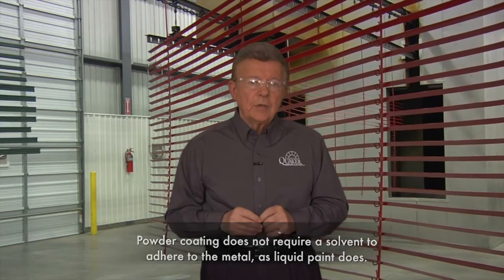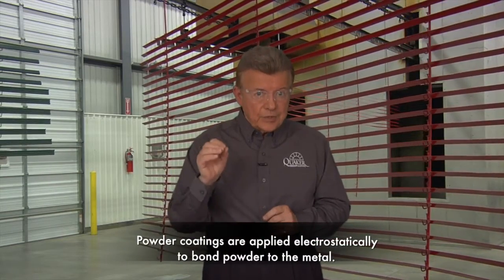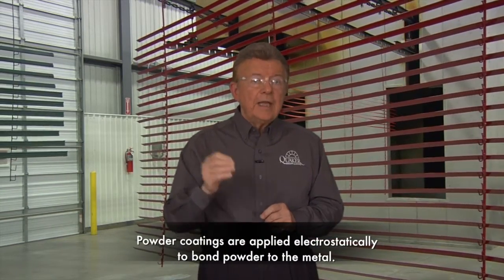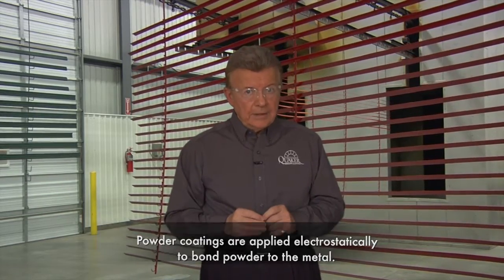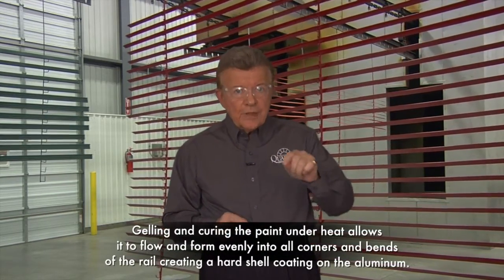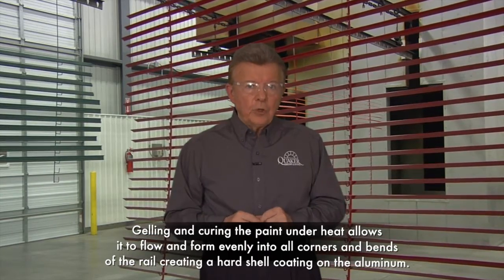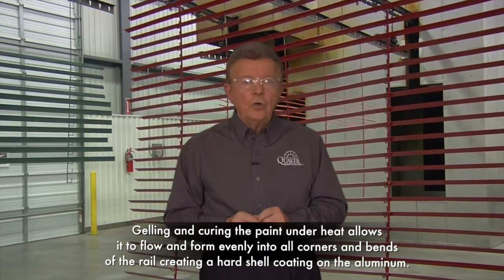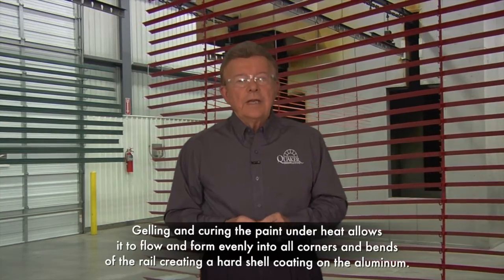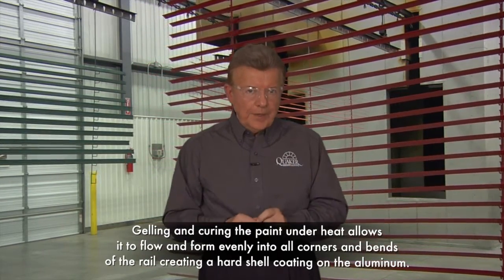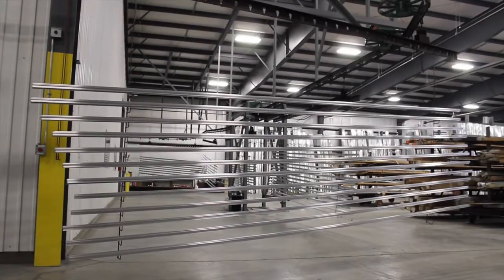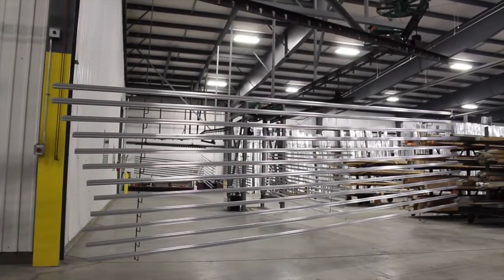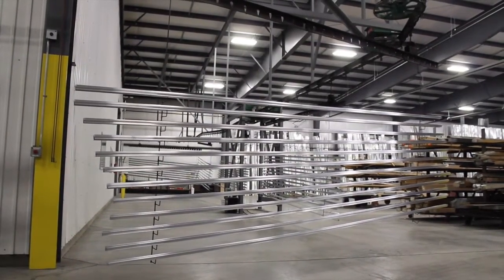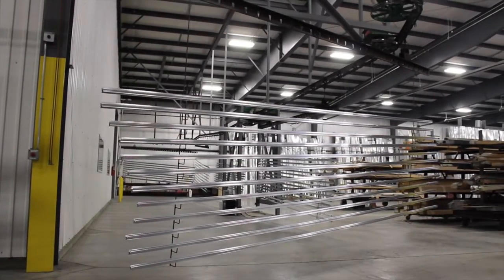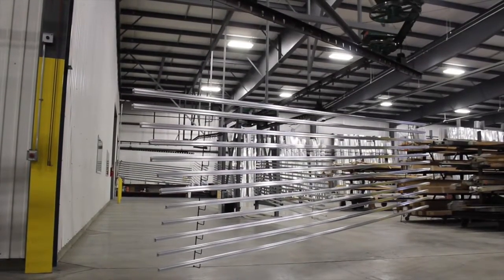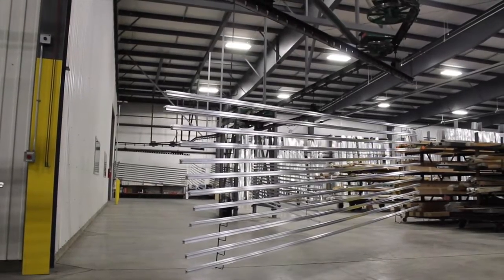Instead, powder coatings are applied electrostatically using charged particles and electric current to attract and bond powder to the metal, and then gelling and curing the paint under heat to allow it to flow and form evenly into all corners and bends of the rail, creating a hard shell coating on the aluminum. Material handlers will hang as much as 15 tons of material each day. Once loaded, it takes each rack about an hour and 45 minutes to travel through the state-of-the-art paint process.